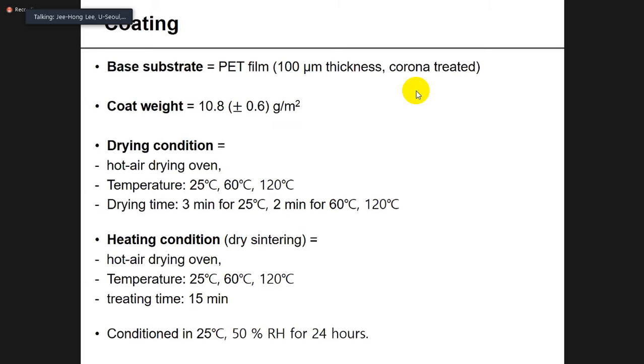The coating layers were prepared on corona-treated PET film, and the coat weight was 10.8. The drying and heating processes were carried out in a hot air drying oven, and the temperature was different. All prepared coating layers were conditioned at 25 degrees Celsius, 50% relative humidity for 24 hours.